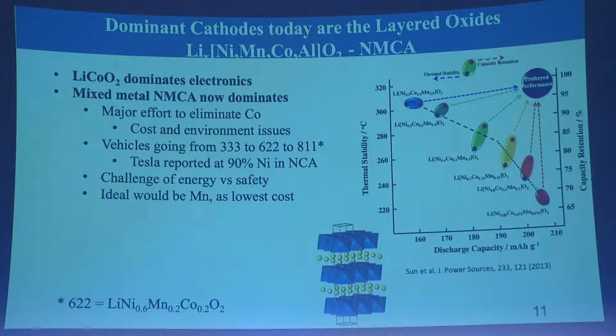Now, we hope we never take these batteries to these temperatures, but this measure of thermal stability is a direct measure of how reactive they are with the organic solvents. So the higher the thermal stability, the less reactive they are. So in essence, the higher the nickel content, the more reactive they are. But we want high nickel for 2 reasons. It gives us higher energy. It takes out the cobalt.